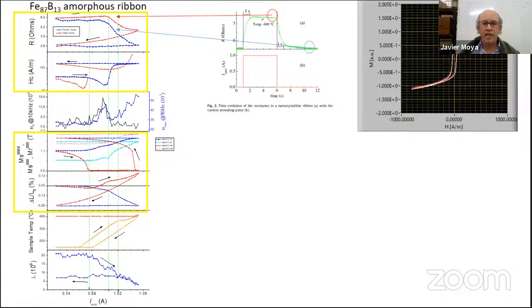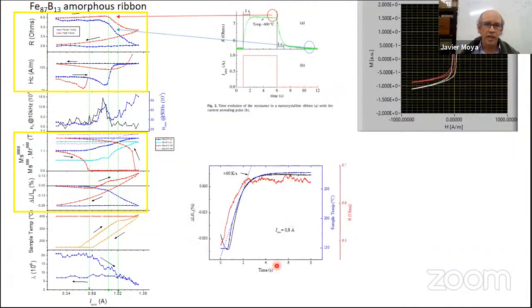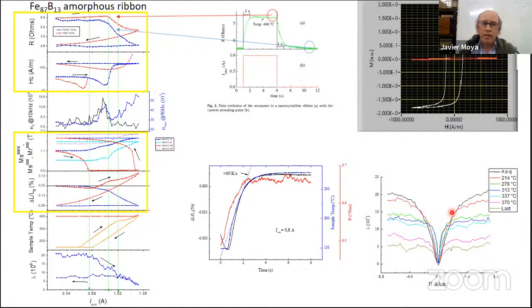All data used to generate each point of this graph is recorded in such a way that one can go to a specific point, for example, here, 0.8 amperes, and see how the heating was. Here is a recording of the hysteresis loop on the way up to the heating. The red one is at high temperature and the white one at room temperature. And here we have some measurements of the magnetostriction as a function of the applied field, also obtained during the same experiment.